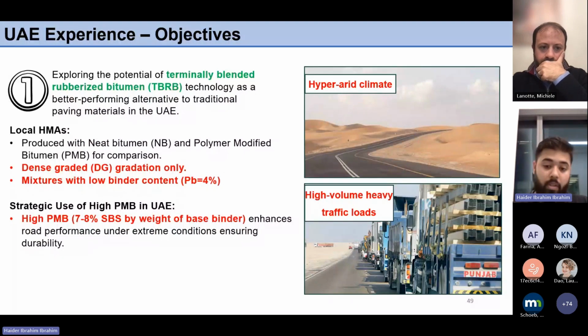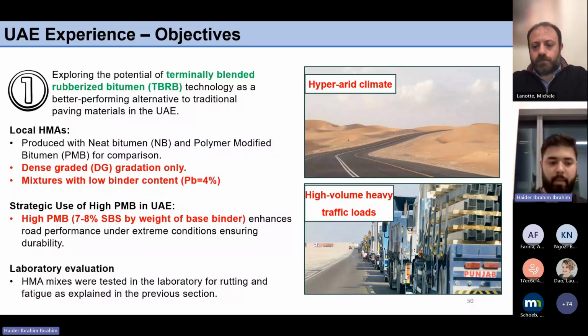And on top of that, the high volume, heavy traffic loads are there. Basically, there are actually no upper limits on the truck weights here. So it's very challenging. And so our objective was to analyze the asphalt with TRB and TBRB and compare it with the typical HMA produced here with neat bitumen and polymer modified bitumen. And for that, we analyzed it in the lab for rutting and fatigue, the same way as Dr. Angela described in the previous section.